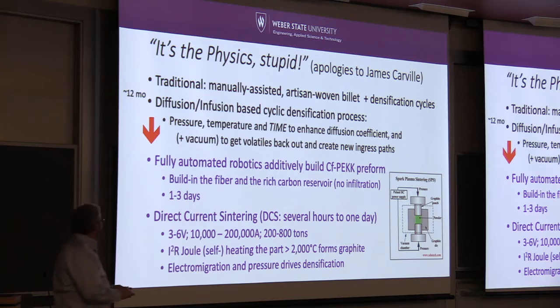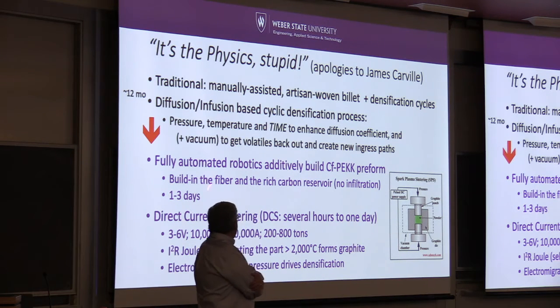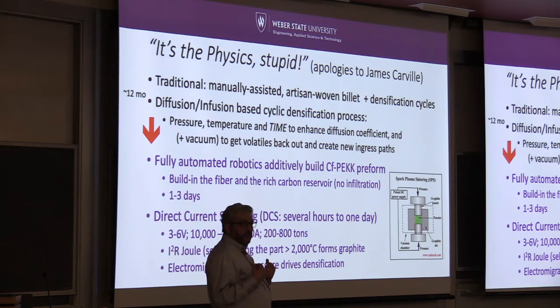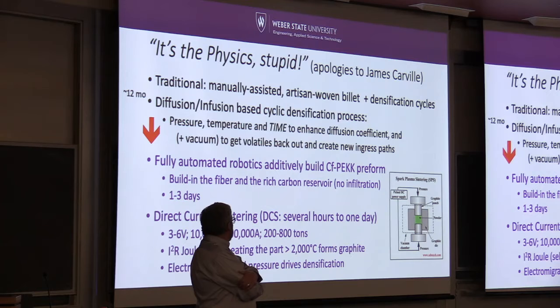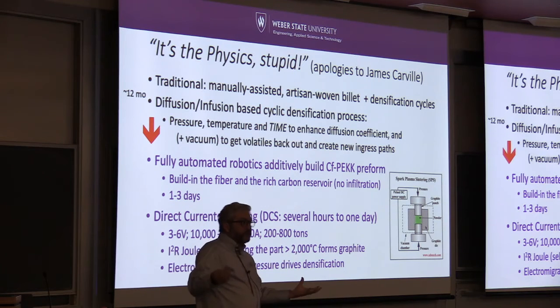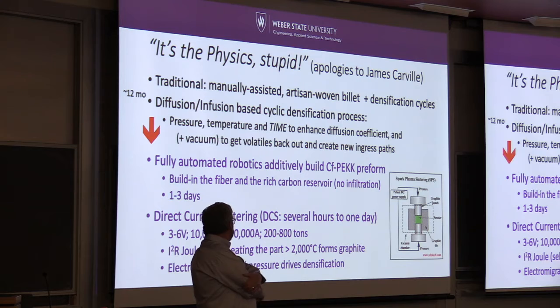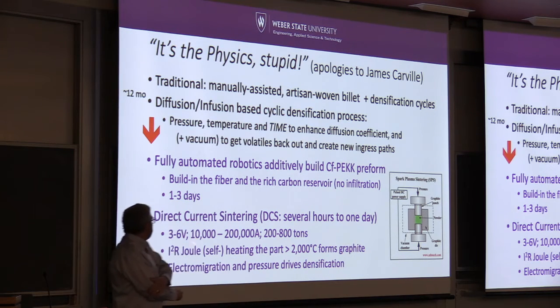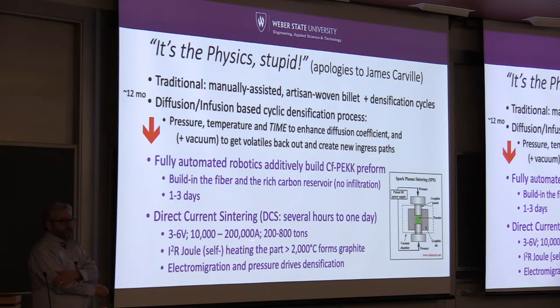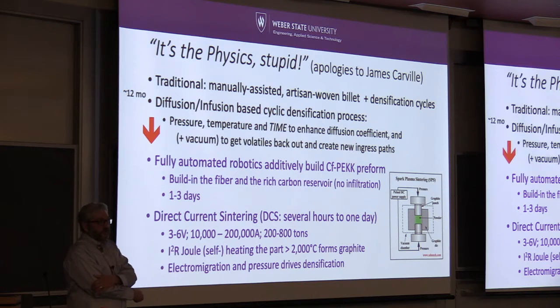So, what about this technique? What we wanted to do was use additive manufacturing, use high temperature thermoplastics, and build the fibers and the resin in such a way that we could do an in situ conversion into carbon-carbon. So here's kind of what you're looking at with this direct current sintering. Very low voltage, but extremely high currents and high current densities, and a lot of pressure. The system at Idaho National Lab is an 800-ton system with a couple 100,000 amps. That's a pretty beastly system. So get it up above 2,000 C, form graphite, and then you're pretty happy.